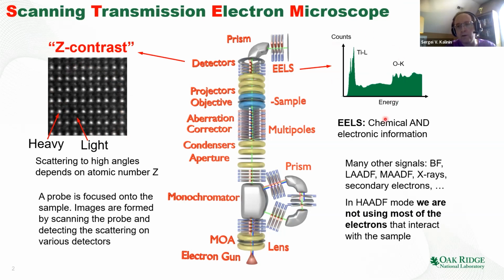Another thing that we can do is we can measure the energy of the electrons that pass through the material. That's very interesting because electron loses the energy by interacting with the nuclei. It loses the energy by interacting with the valence electrons. It can lose energy interacting with the quasiparticles. And in this manner, we also learned the chemical and quasiparticle excitations inside the material.